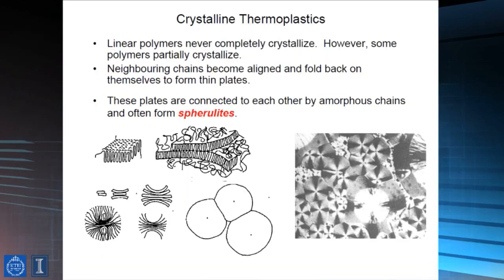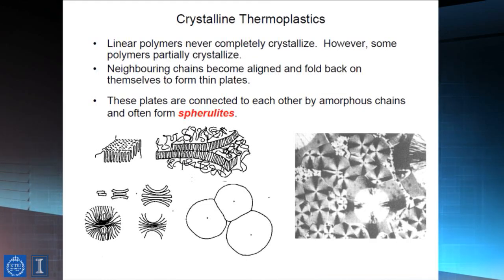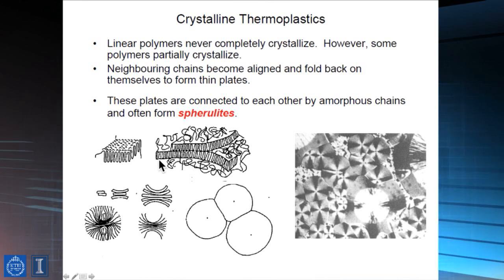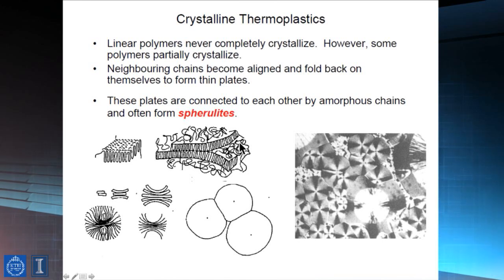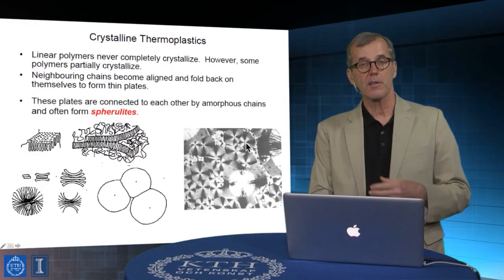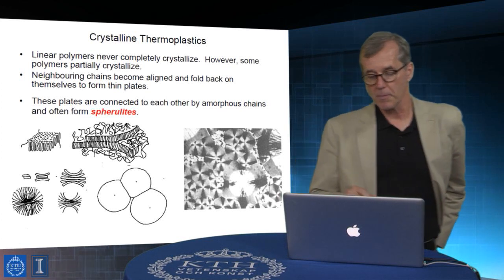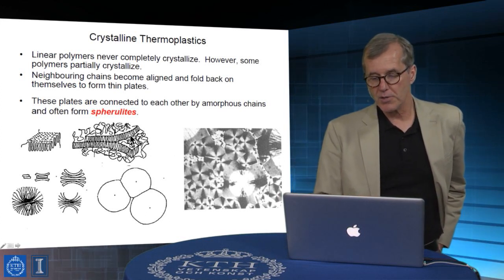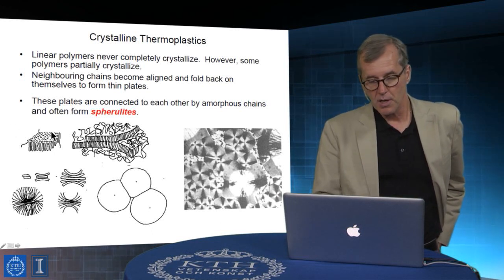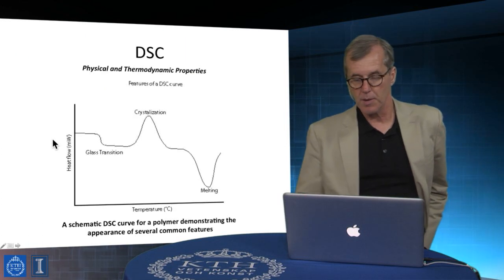This is an example of a polyethylene sample looked at under crossed polarizers. And you see these beautiful structures that show up if you look at thin films of crystalline polyethylene this way. And these are so-called spherulites, which are these domains of lamellar sheets that have basically bends in them because they also entrain some materials that are less ordered, that give them these beautiful structures that are reminiscent of the dislocations that we talked about in liquid crystalline cases. But these are actually the anisotropies associated with the organization of essentially lamellar sheets of chain-folded polymers.